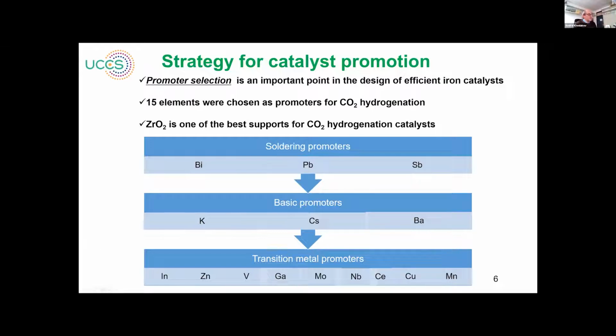So here are the promoters which have been used. First are soldering promoters, which are metals with relatively low melting point. There are several soldering promoters which can be used. These promoters were very efficient for conventional Fischer-Tropsch synthesis. We also tested basic promoters such as potassium, cesium, barium, and also a significant number of transition metal promoters.